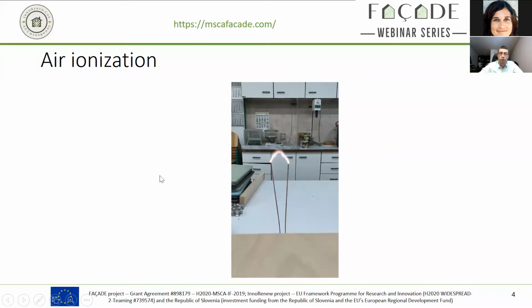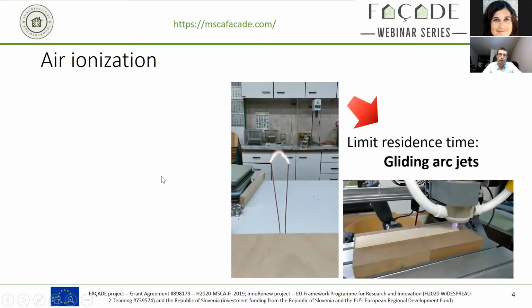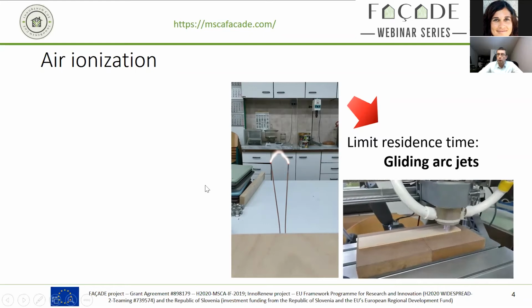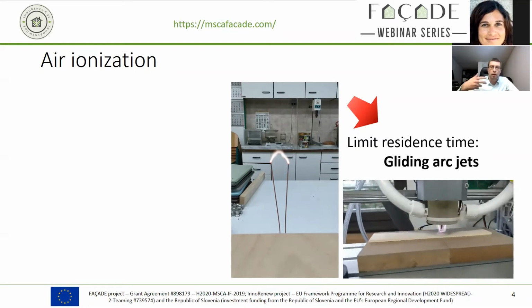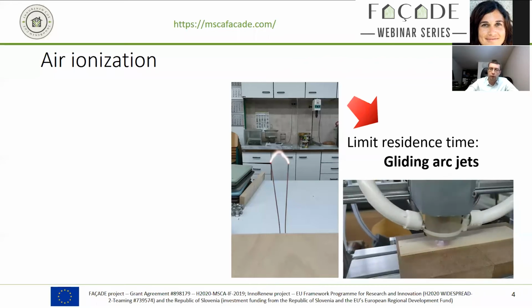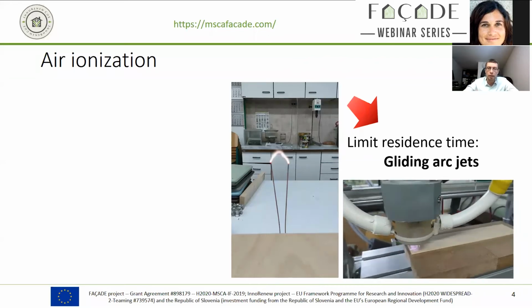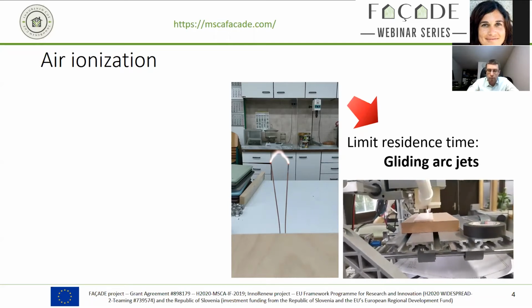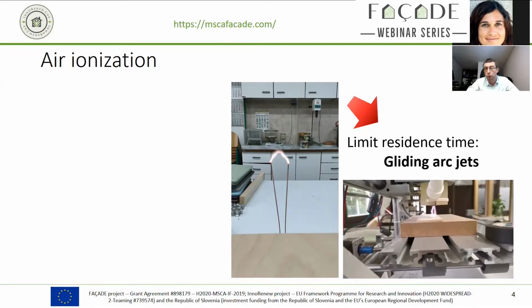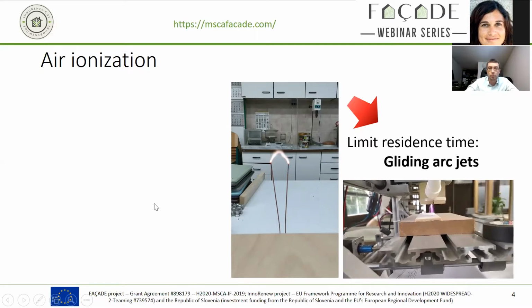And there's certain ways to avoid this. The first way to avoid this kind of arc formation in this hot state, like we see in the middle, is just to limit the residence time. So to put this into a nozzle, to provide a high enough flow velocity of the working gas that we are using. This is the way to create a gliding arc jet. So this arc that's igniting is running down the electrodes, and the ionized gas with all those reactive species is advanced onto the surface. So these are typically local treatments, and in most cases require either a movement of the sample or a movement of the plasma device. But it's something that's relatively easily arranged and widely available throughout all different industries.